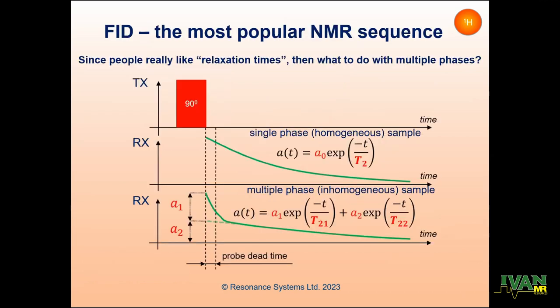But actually, it's not only the relaxation times, especially when you are dealing with solids, with multiple phases in solids. So you normally see different contributions. And even if you are talking about exponential relaxation, in many cases you are going to get a signal that can be decomposed into different components. And these different components have different contributions, and they might have different relaxation times. And this is already more interesting, and this brings really more information. So a single relaxation time is just something very much simplified. So my message is that time domain NMR is much more interesting and can bring really more information about the structure and dynamics of samples.